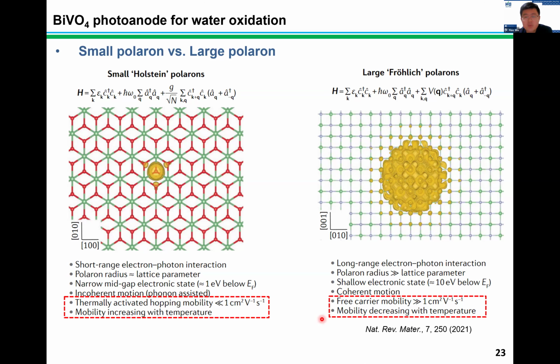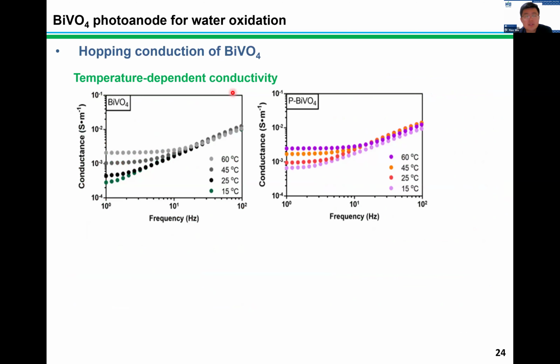Based on this understanding, we first did temperature-dependent conductance measurements on our samples. We prepared 2 samples with and without phosphorus doping. And we increased the temperature, and we found that the conductance of both samples increased with rising temperature, indicating their hopping conduction behavior, no matter with or without phosphorus doping.